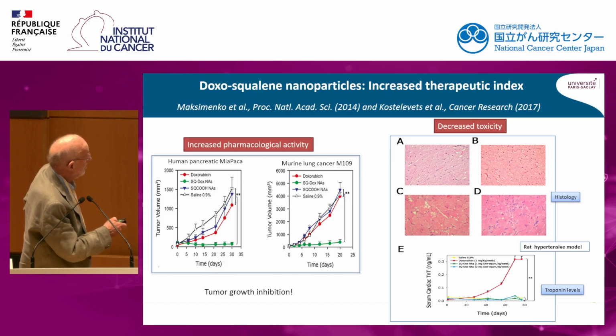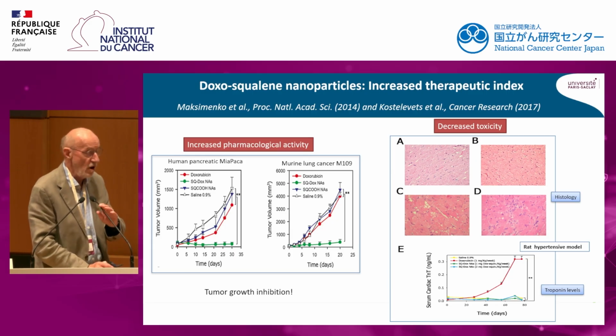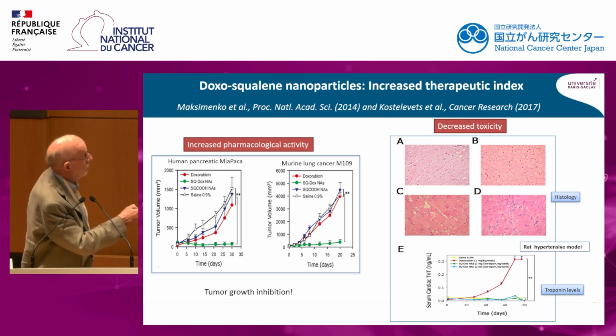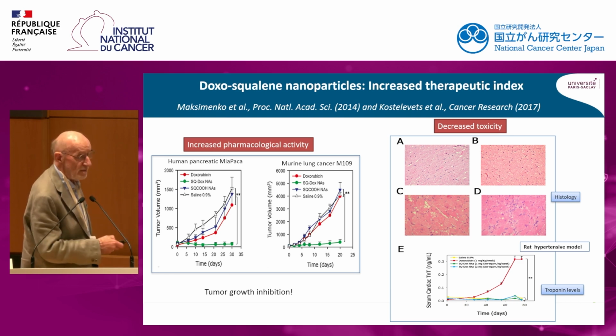You can see that those experimental tumors are absolutely resistant to doxorubicin injected as a free molecule here in red, and that after administration of the doxorubicin squalene nanoparticles, you completely inhibit the tumor growth. And also we decrease the toxicity dramatically.